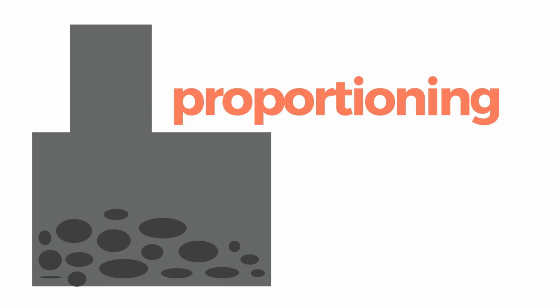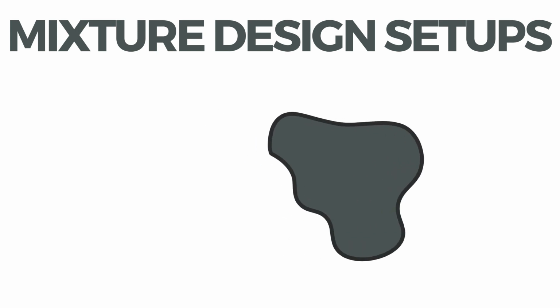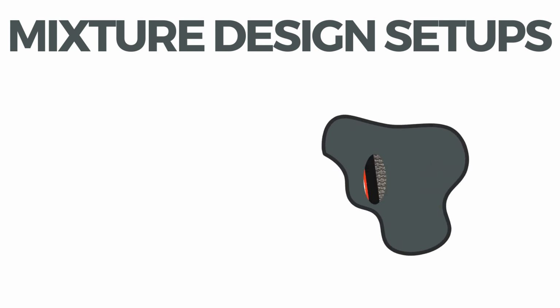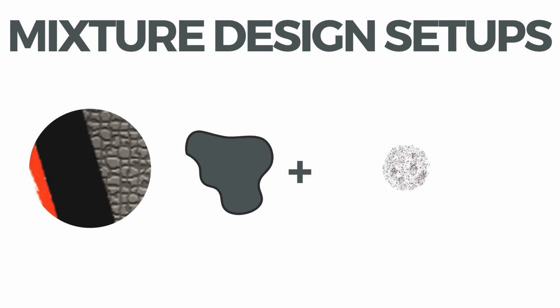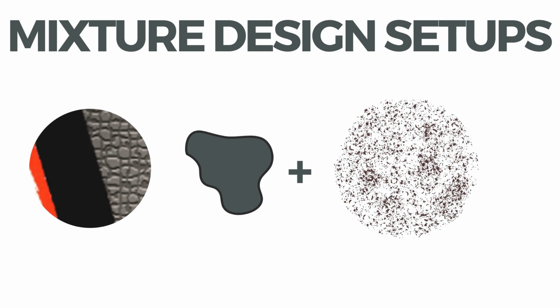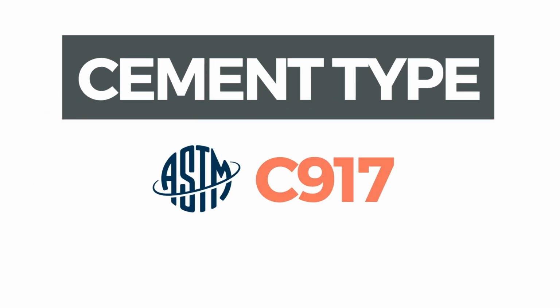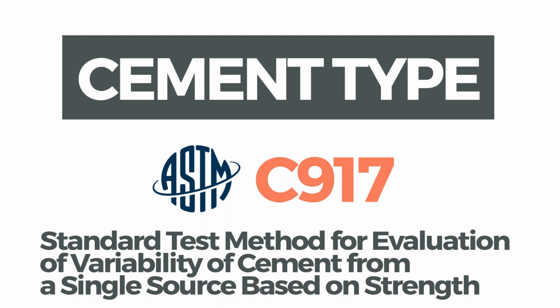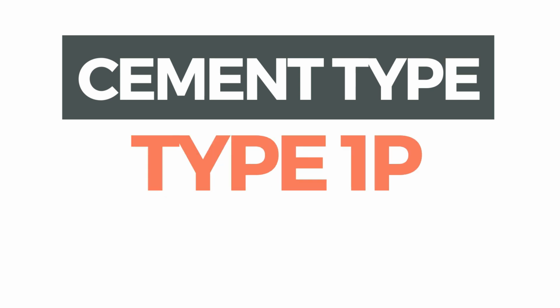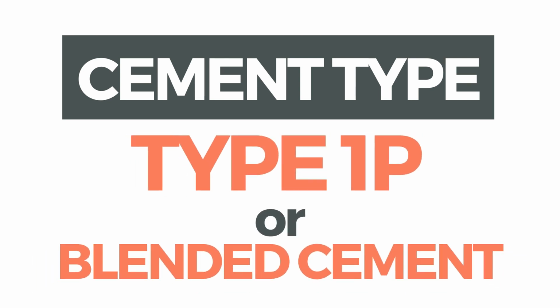In formulating the proposed mix designs, proportioning by weight method will be used. The mixture design setups will be composed with variation in the composition of the aggregate binder, where extracted copper tailing powders is to be added with varying proportions. Selection of the cement type and source is in accordance with ASTM C917 or standard test method for evaluation of variability of cement from a single source based on strength. Type 1P cement based on the optimal content will be used.